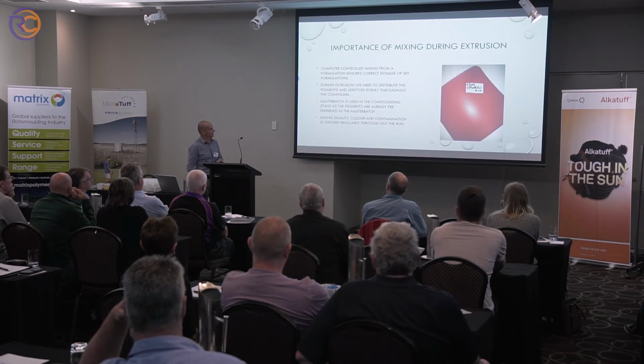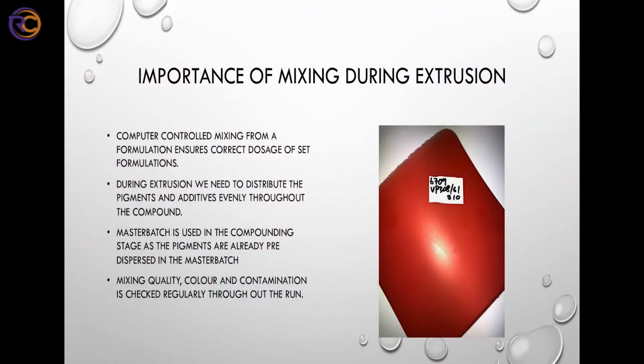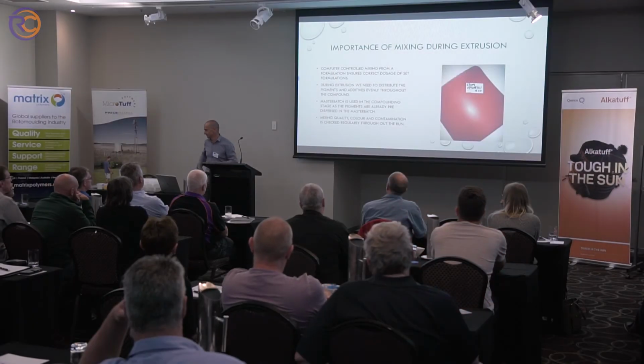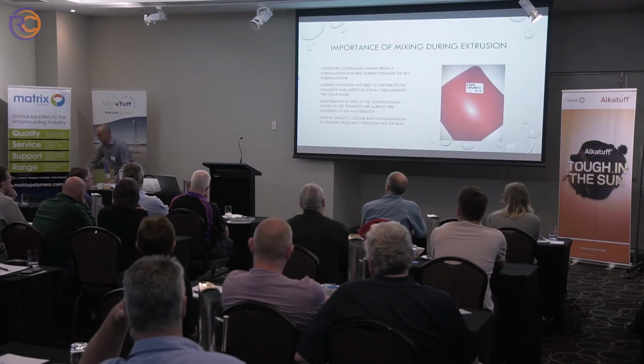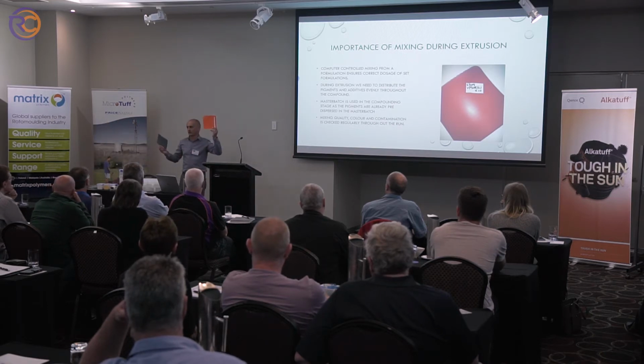Master batch is used in the compounding stage as the pigments are already pre-dispersed in the master batch. The mixing quality, colour and contamination is checked throughout the run. So, I've got some examples here of plates, and this is orange, obviously, and grey. The orange is well dispersed material, and the grey is not so well dispersed.